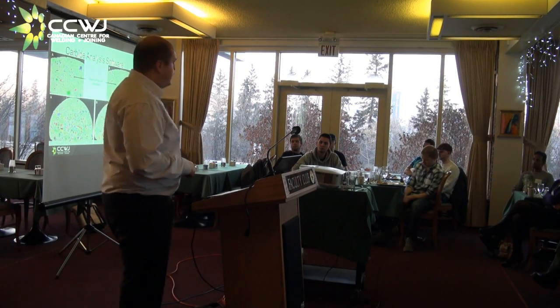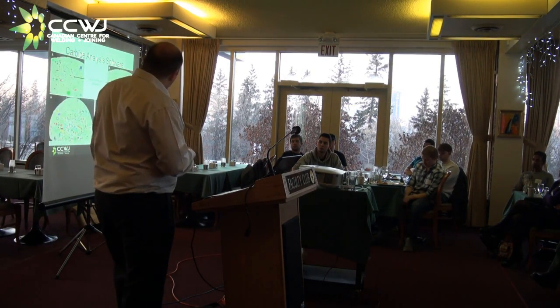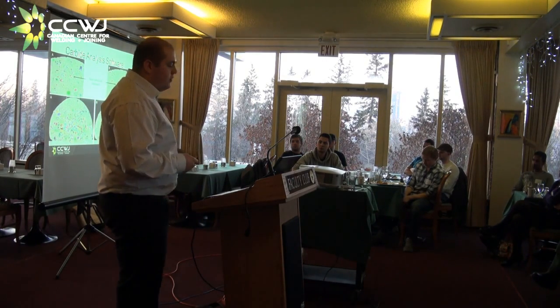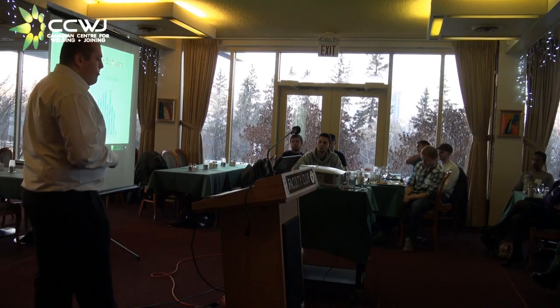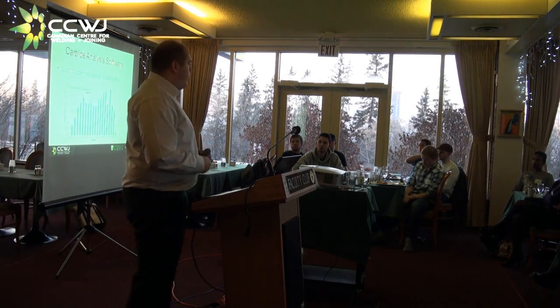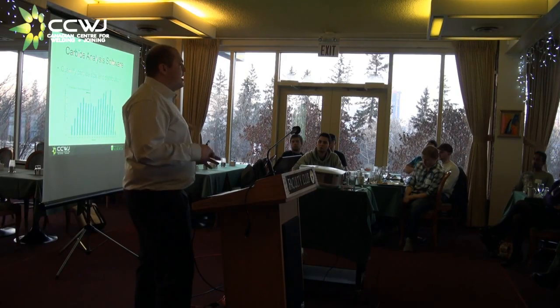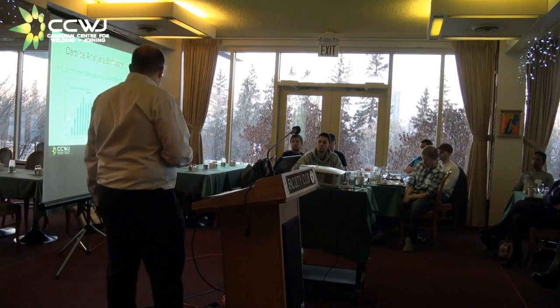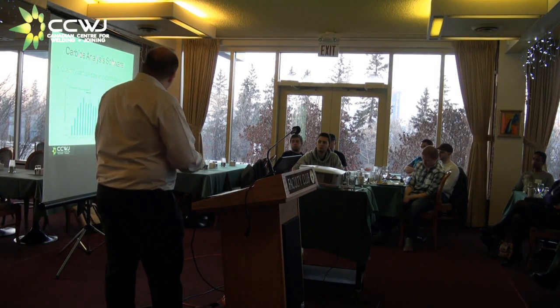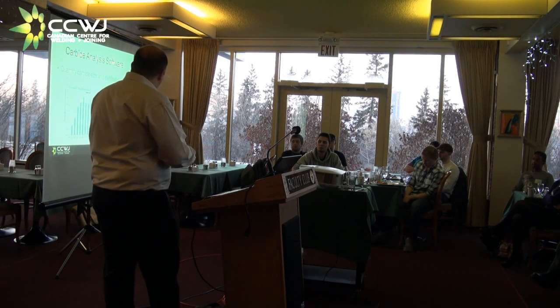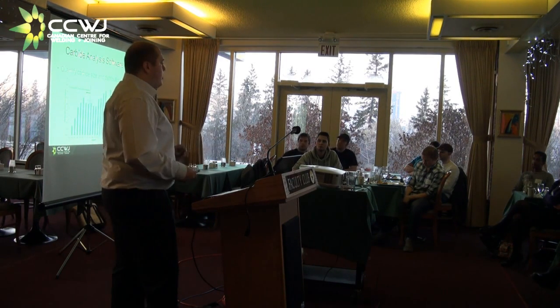And this is very important because the primary ones do give us our wear performance. As a result of all this image analysis, we can now quantify the carbide size and the distribution in the welded deposit. Basically, in this image, here we have our carbide size, and this is an arbitrary point, but we just said that any carbide smaller than 30 microns was reprecipitated. They would not help us in our wear performance in service. And this is something actually really important.